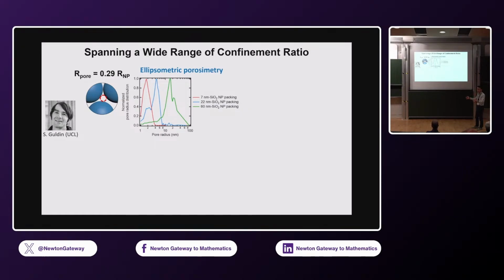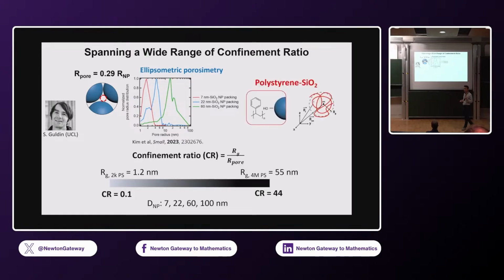There is, of course, a distribution of pore sizes, but the characteristic pore size can be very well defined by simply changing the nanoparticles. Then, of course, the size of the polymer can be varied by just choosing polymers of different length. So by doing this, we can define something called the confinement ratio, which is the ratio between the characteristic size of the polymer to that of the pore. And by doing this, we can span very large ratios, from 0.1 up to 50 or larger.